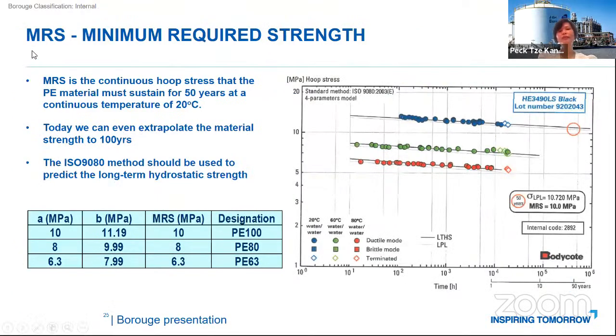So allow me to talk a little bit about MRS testing. MRS is the minimum required strength that characterizes a PE material for pressure application. It is a test that will take us up to 1 or 2 years to complete, to certify that the material can go into a pressure pipe application. As you can see here, this is a very standardized way of demonstrating that the material has been evaluated for its MRS. We have about 90 pipes tested at 3 different temperatures with a spread of hoop stress, and then we do an extrapolation to reach 50 years and find out what this hoop stress level is.